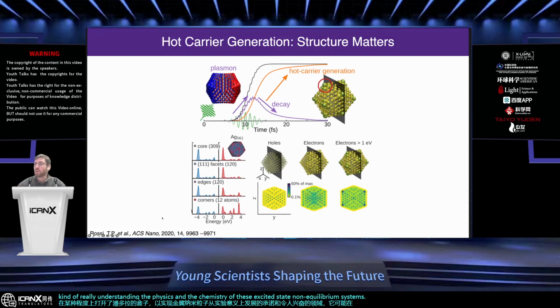So in this paper from 2020, published in ACS Nano, they used TD-DFT for the generation of a plasmon resonance in a small silver nanocluster. And what this group was able to show is that hot carrier generation and localization actually prefers to occur on places of under-coordinated sites within the nanoparticle itself. So based on computational restrictions, this is only a 561 atom cluster, so that would translate to a 2 to 3 nanometer particle. But what they see is that the electrons in these systems are actually going to localize at the corners. So you can see these areas of high electron density. So electrons with greater than 1 eV of energy, they localize at the corners. You can see some electron localization towards the edges. And these are, of course, on very, very fast timescales.